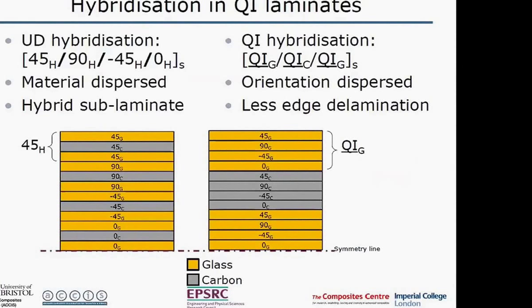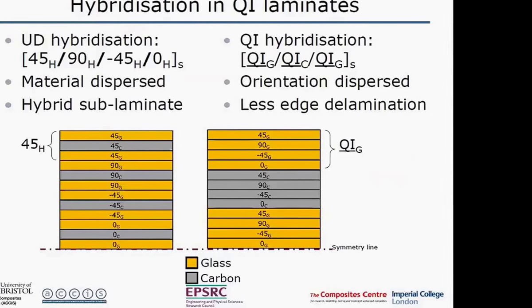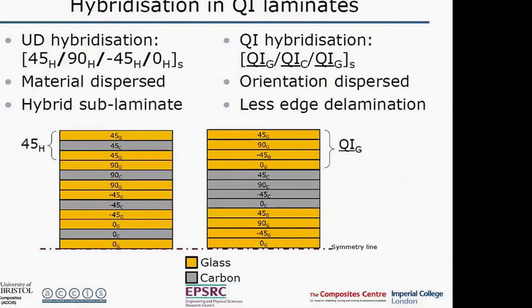Going on then to look at making laminates of this material, we want to make a quasi-isotropic laminate. We've got two different ways that we can do that. So one way is to make a hybrid sublaminate, where we take, in this case, glass, carbon, glass, all of the same orientation. And then we take a 45 block, then we do a 90 block, a minus 45 block, a 0 block. So we make a quasi-isotropic 0/90/plus-minus 45 laminate, where each of those layers corresponds to a sublaminate. So it's like you can define a pseudo-ductile prepreg, which has got these different combinations of materials, the same orientation, and then you lay that up like this through the thickness. So we refer to this as a material dispersed configuration, and it enables us to use these hybrid materials like an ordinary material and just lay it up in a normal way.